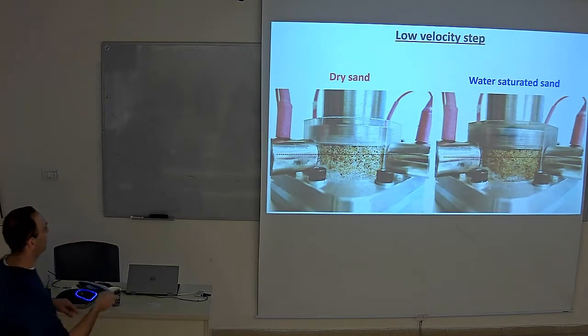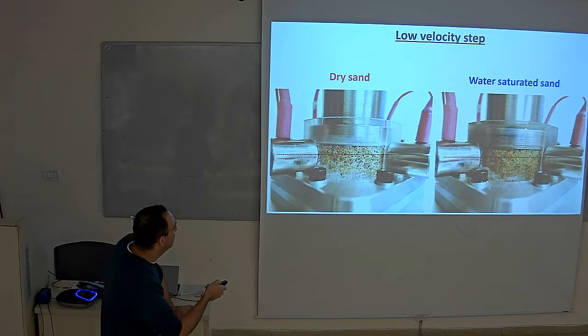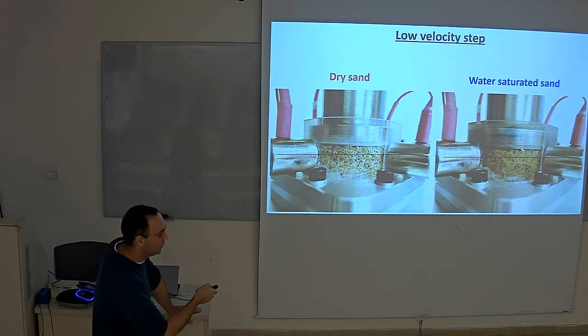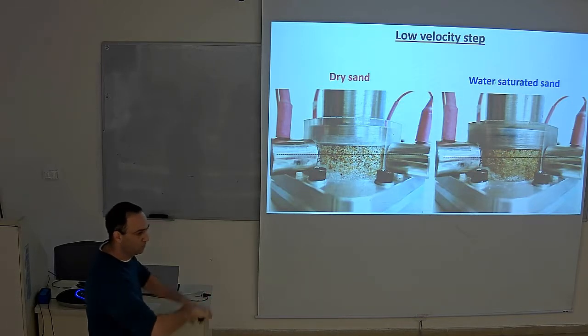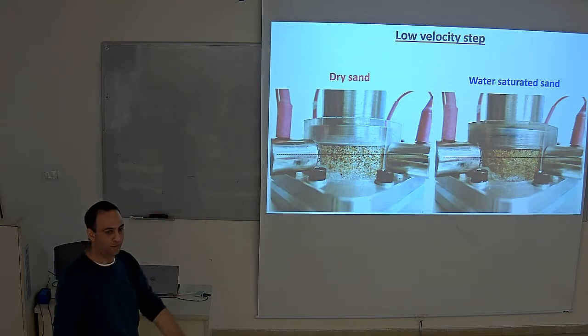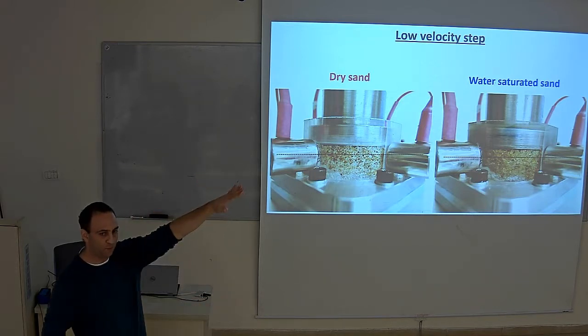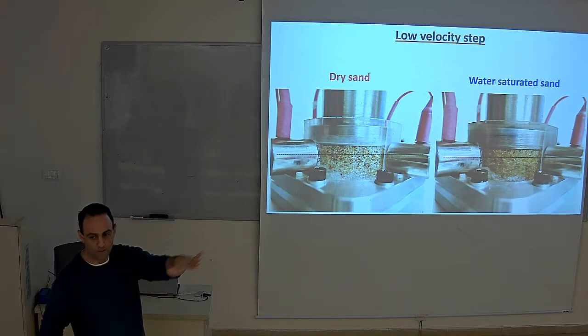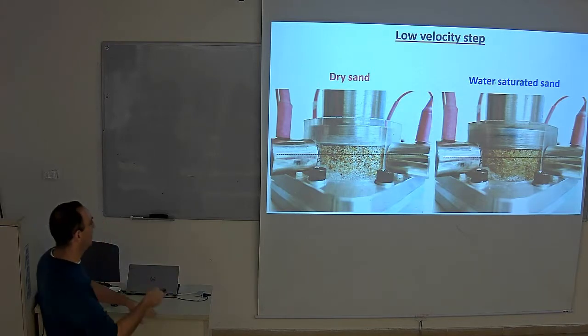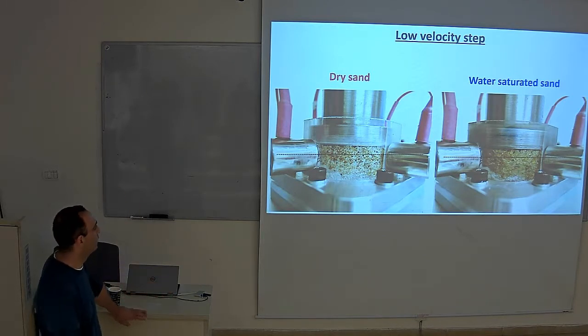However, I want to say something else here that I don't know if you can see. Here on top, this is the water, and you can't really see the steel rotor behind, so it's a puck. What's going on is that the material that's crushed during the high velocity step is injected outside with the water to the upper parts, and then it's just deposited on the surface. And if you remember the gradual decrease of the water saturated experiments, I think it's because of the injection of material and removal of particles, of mass, out of the system.